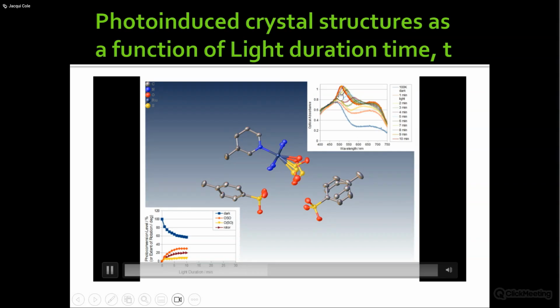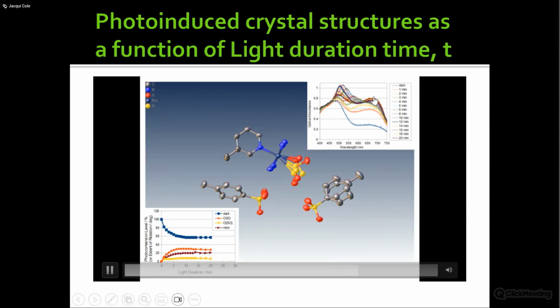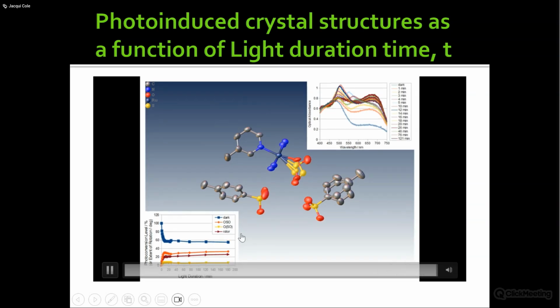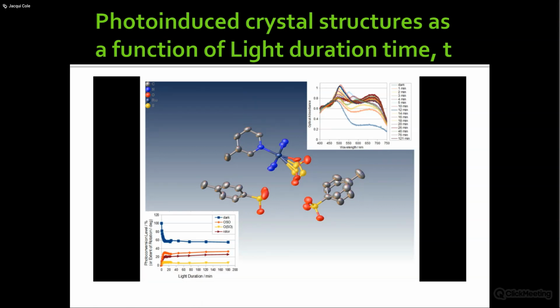Something saturating there, and then actually it comes over the edge of that and then starts to decrease, and you actually see the optical absorption at the sort of redder side increase, right? And then after a while it settles, and then it sort of slides away. And so, having got all that information, now we've got this correlated information between optical absorption spectroscopy and crystallography, really seeing every single structure at each instant.